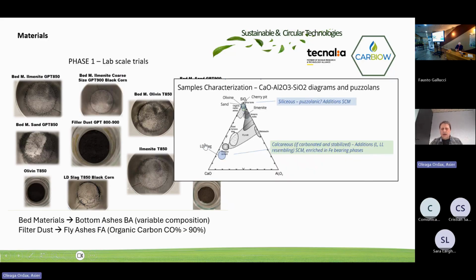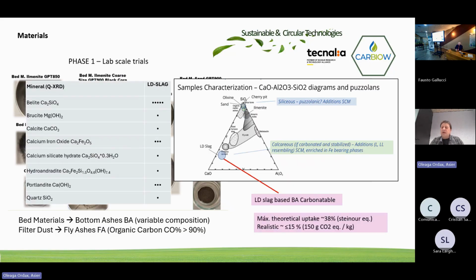In this case, among all the materials, only LD slag based bed materials were really carbonatable. The other ones were really siliceous, like olivine, sands, silica, ilmenite, that can be useful for applications, but not for carbonation. The maximum theoretical uptake can be 38% per weight, but realistic after looking to the mineral phases, we expected to capture about 150 grams of CO2 per kilogram of sample.